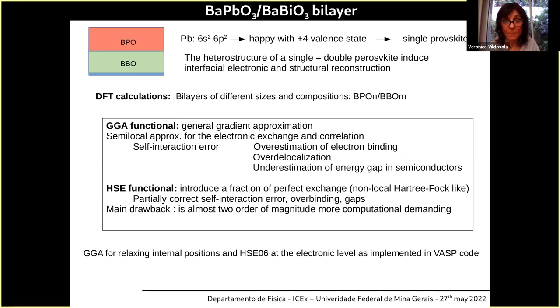So one way to partially correct this self-interaction error of the local functional is to introduce a fraction of a perfect exchange-like interaction, like the non-local Hartree-Fock interaction, which doesn't have, by construction, the self-interaction error. So you correct this self-interaction error with this hybrid functional. You partially correct this error and the overbinding and the gaps. The main drawback is that it is almost two orders of magnitude more computationally demanding.